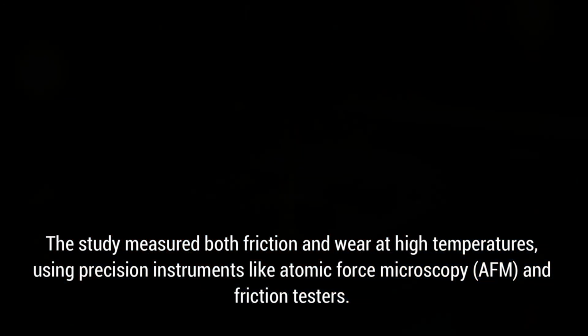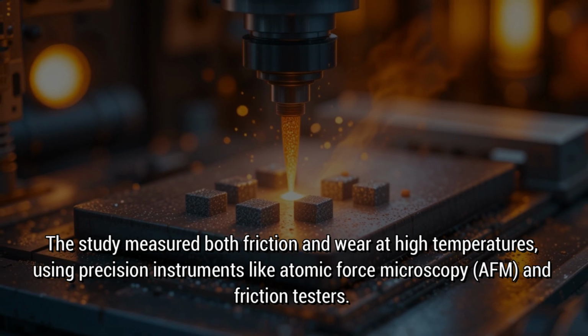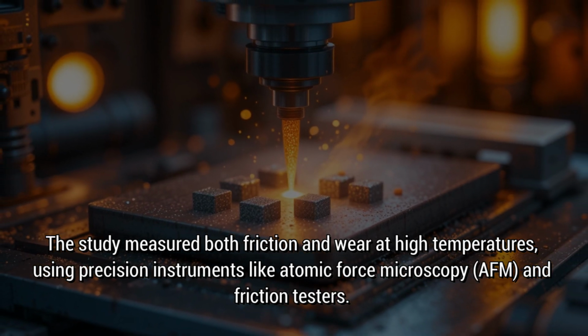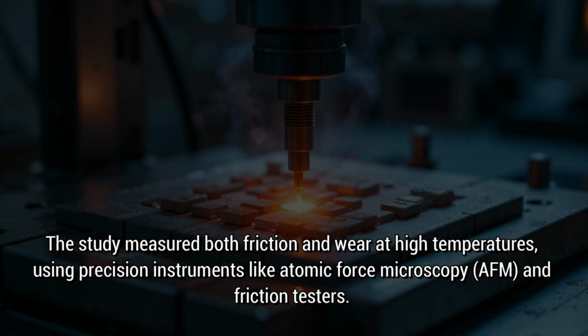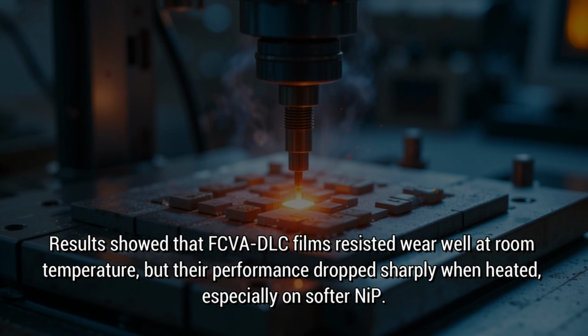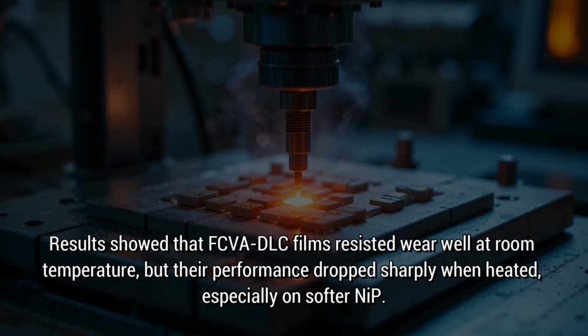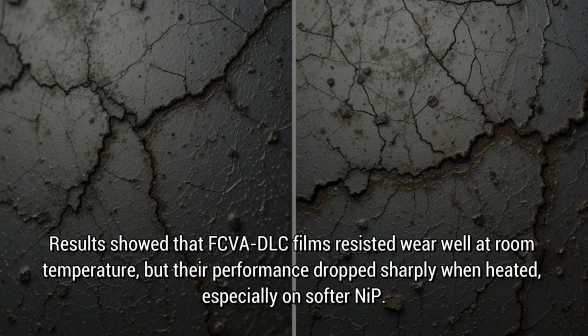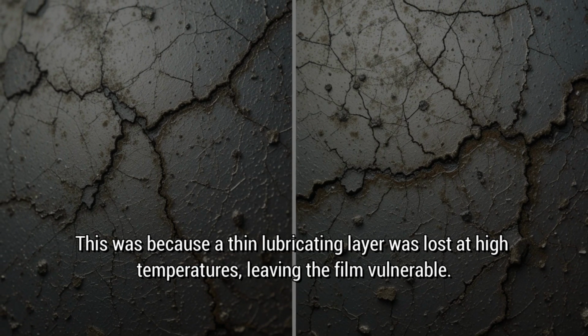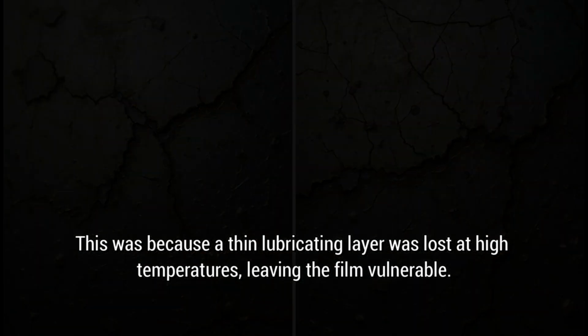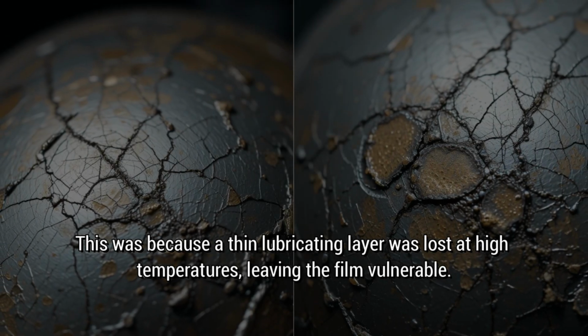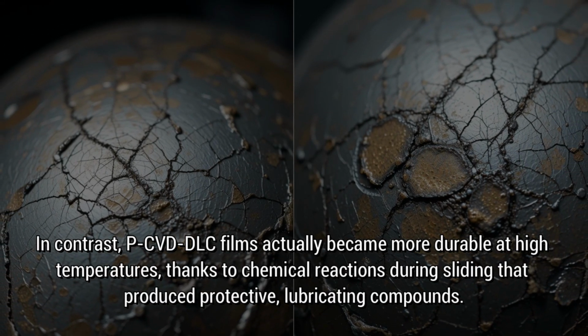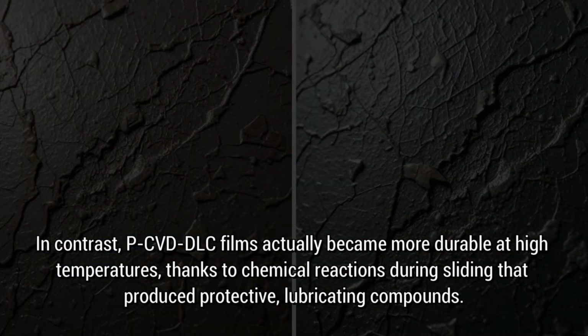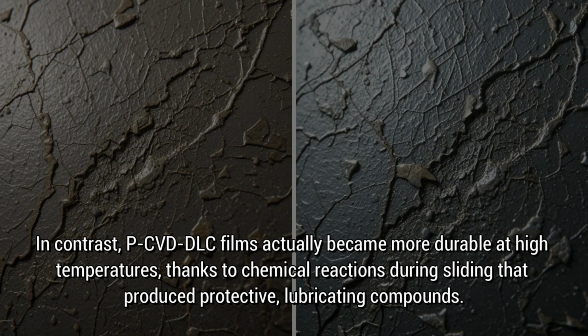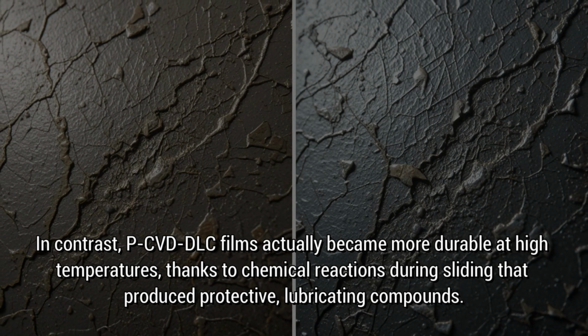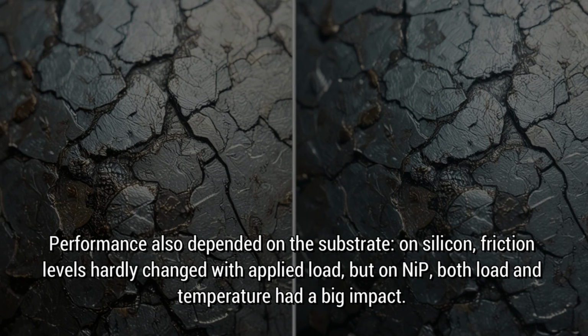The study measured both friction and wear at high temperatures, using precision instruments like atomic force microscopy, AFM, and friction testers. Results showed that FCVA DLC films resisted wear well at room temperature, but their performance dropped sharply when heated, especially on softer NiP. This was because a thin lubricating layer was lost at high temperatures, leaving the film vulnerable. In contrast, P-CVD DLC films actually became more durable at high temperatures, thanks to chemical reactions during sliding that produced protective, lubricating compounds. Performance also depended on the substrate.